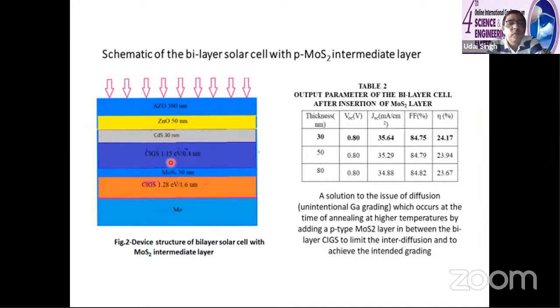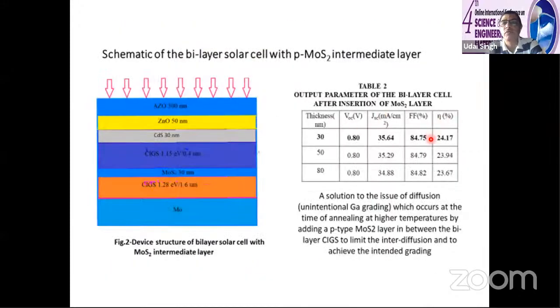So what we have proposed for the first time is, if you use moly sulfide, we have optimized for different thicknesses. 30 nanometer has given the best efficiency. This will prevent gallium grading, and this is done in the simulated work. Different parameters have to be optimized. This has given us the best efficiency of around 24.17.